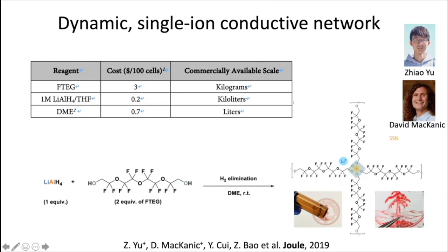So here we have the aluminum center coordinated with four oxygen, so as to create a negative charge. So that would become the site that can solvate the lithium ion and allow the transport of lithium ion in the single ion conductive mode because these sites are localized in the polymer network. And then we choose the polymer backbone to have these fluoro ethers. And if it's all fluoro ether based, then it doesn't solvate lithium ion, so it doesn't swell by the solvent. So this provides a network that doesn't swell, but has the single ion conductivity from the aluminum site.